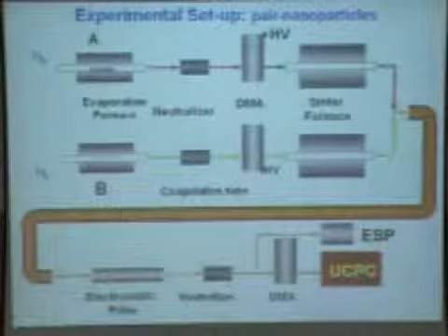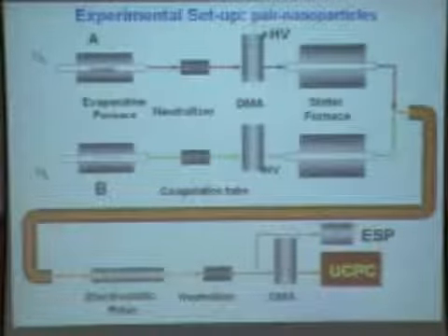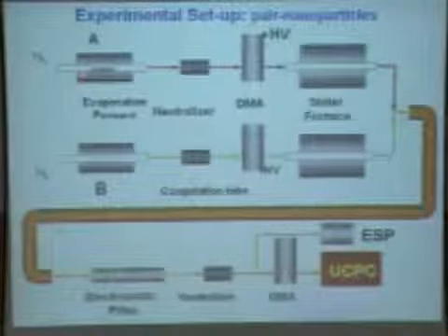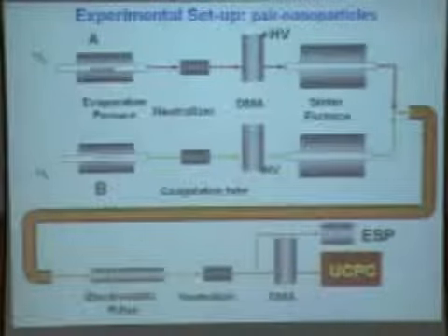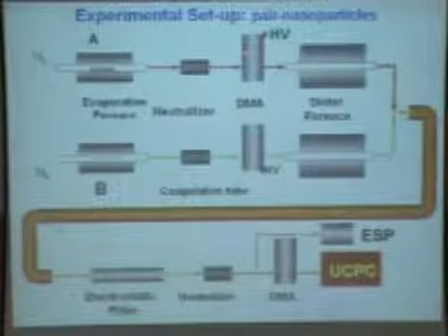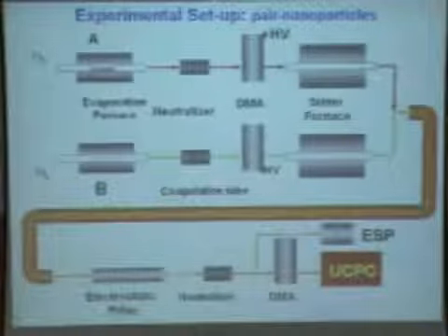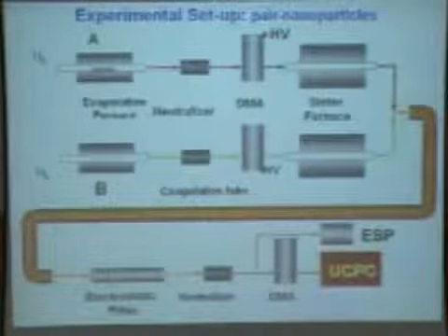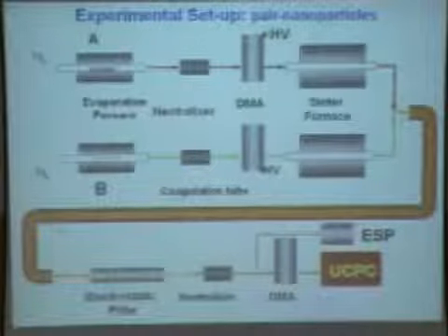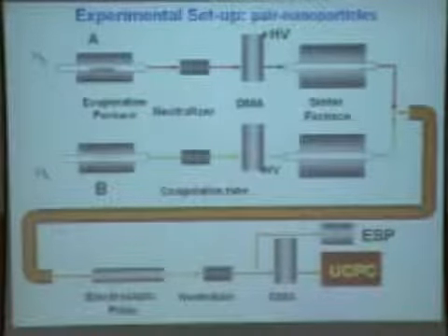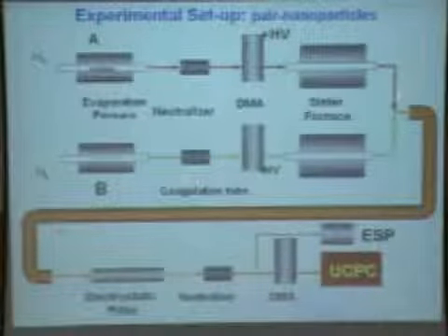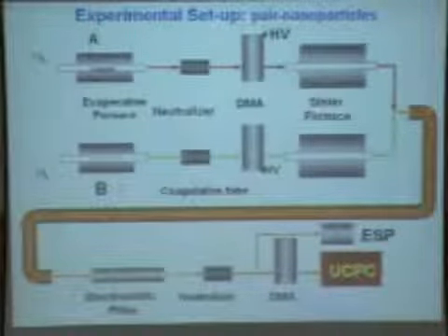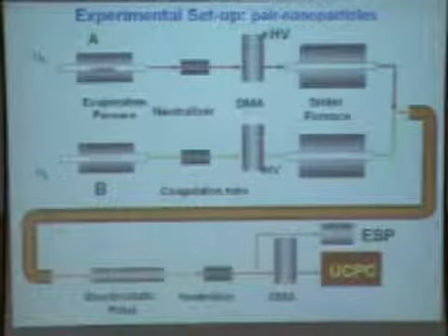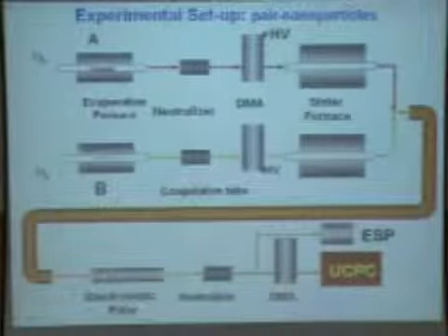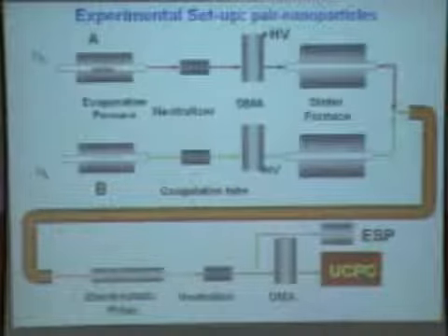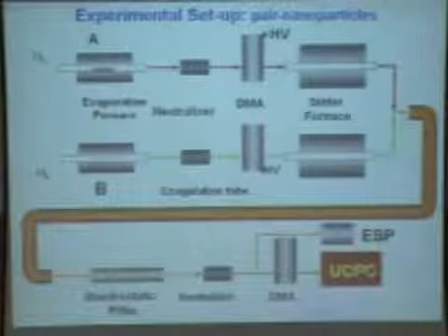This is another extension of the same synthesis setup which we are using presently. As I mentioned earlier, this is the evaporation furnace or a spark generator. Then we have a charger, a DMA, and a furnace. Let's say we keep the central electrode positive, then the nanoparticles which come out will be negatively charged. So you have material A, negatively charged particles come out and go into this tube. In this DMA, the central electrode is kept negative. Here you have material B, and what comes out will be positively charged particles.